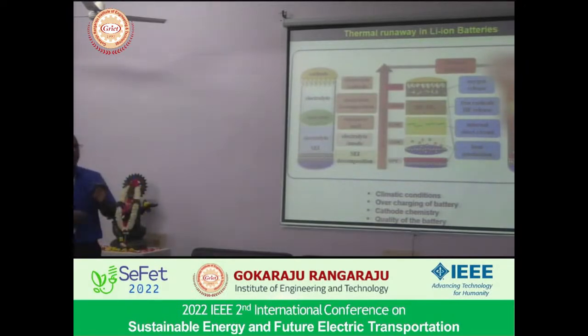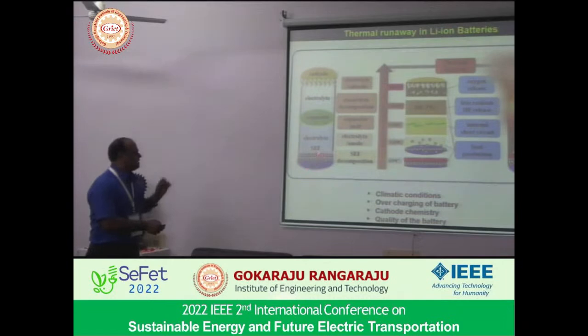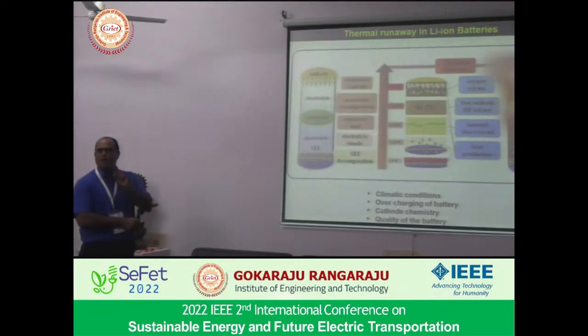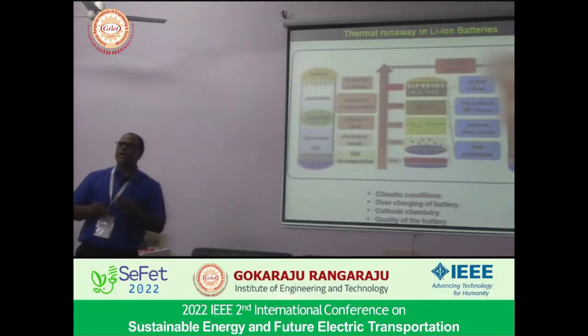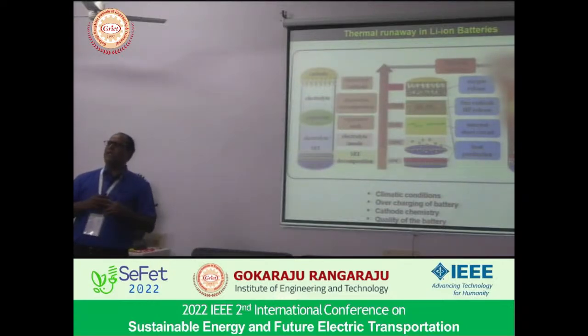During charging and discharging, the solid electrolyte interface forms, and it contains lithium carbonate. When the temperature goes above 60 degrees, first this solid electrolyte interface decomposes, and then the temperature slowly keeps increasing. The liquid electrolyte, which is all carbonate solvent that we are using, is highly flammable.